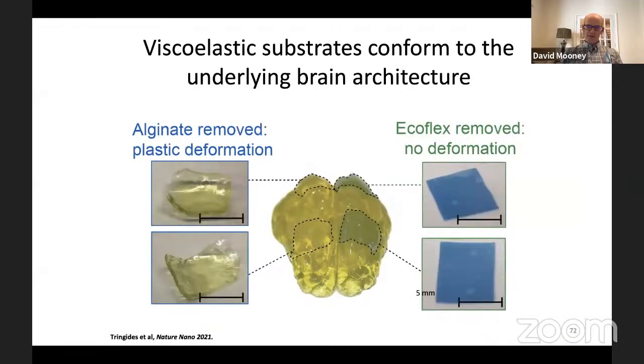These viscoelastic arrays actually conform to underlying brain architecture very well. So here we're looking at an agar model of a sheep brain. And if we use EcoFlex, a typical material, it doesn't conform very well to the underlying brain tissue. When you remove it, you can see it has undergone no deformation. When we use one of these alginate materials instead, it will actually plastically deform or flow to precisely match the underlying geometry of the brain tissue, as one can see when it's removed after some period of time.